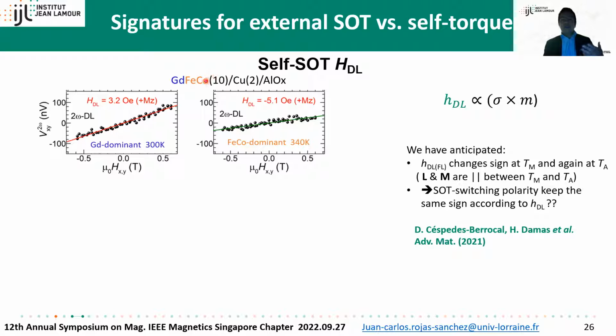Here is the magnetic layer itself that we are manipulating. In this case, we have a bilayer. We observe that at low temperature, when the system is gadolinium dominant, we have one slope, and at high temperature, above the magnetic compensation temperature, we have the opposite slope. That means, following this simple relationship, that the damping-like field changes sign.